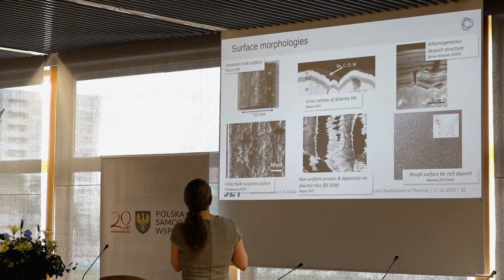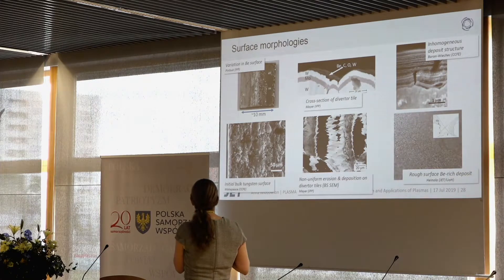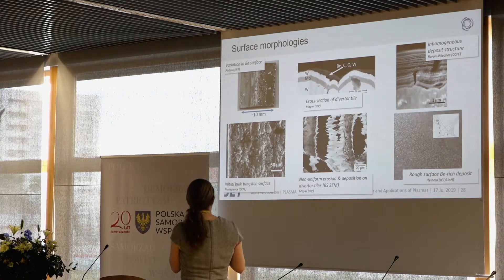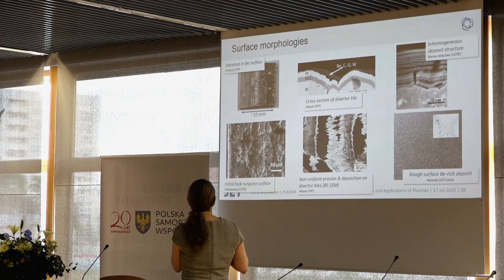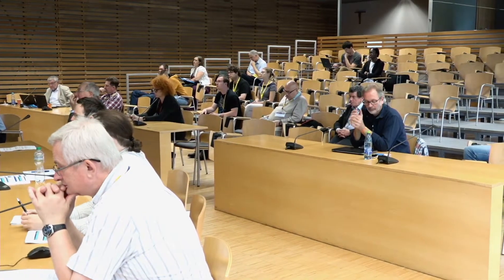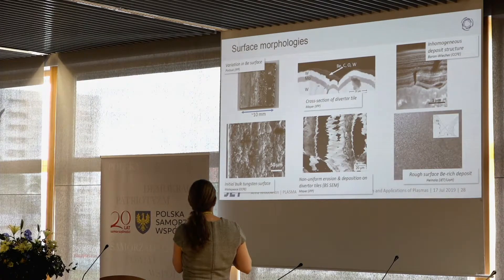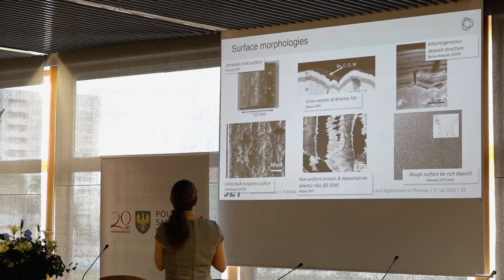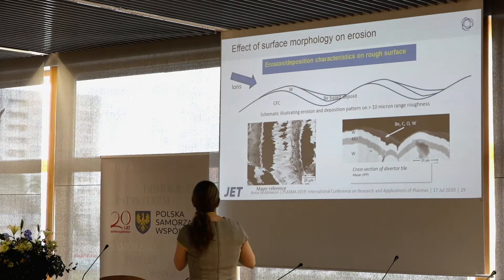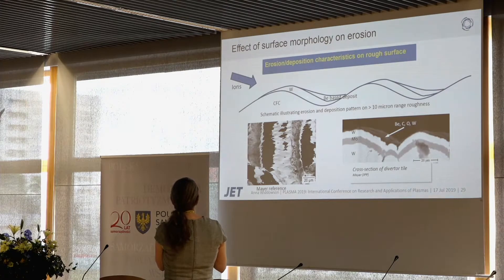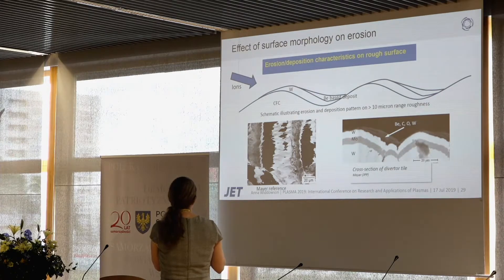Looking at the carbon fibre composite with tungsten coating: you can see the tungsten coating on the CFC, and beryllium accumulates in the valleys of this rough surface. To even more extreme levels, the carbon fibre composite is exposed, the tungsten coating is visible, and beryllium is in the valleys. Ions come in, erode the surface, and move material into these valleys where fuel and deposits remain.